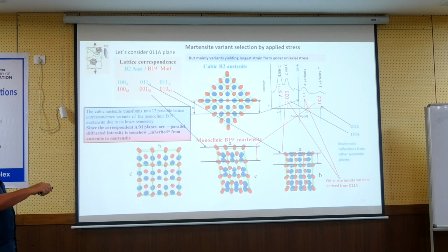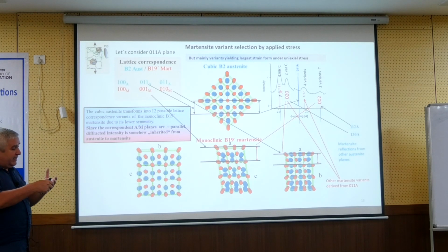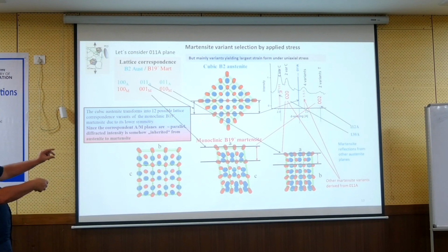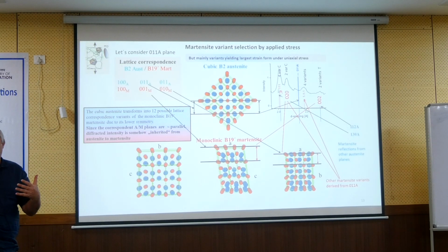So this pattern will appear here if no stress is applied. But if I apply this stress, and now I look at diffraction on this plane, mainly almost all variants will be extended. So the variants which provide the shortening of lattice planes, which is this one, will go down and this one will go up, and this is what we see in diffraction patterns of deformed martensite.